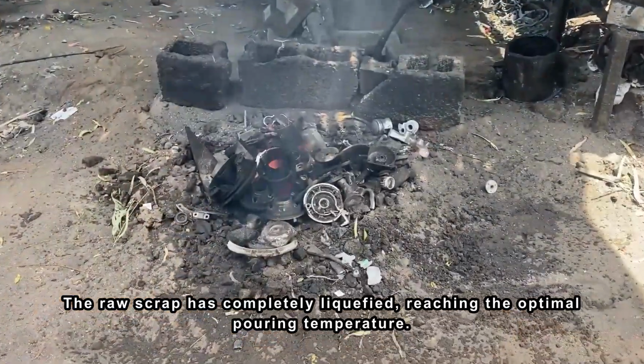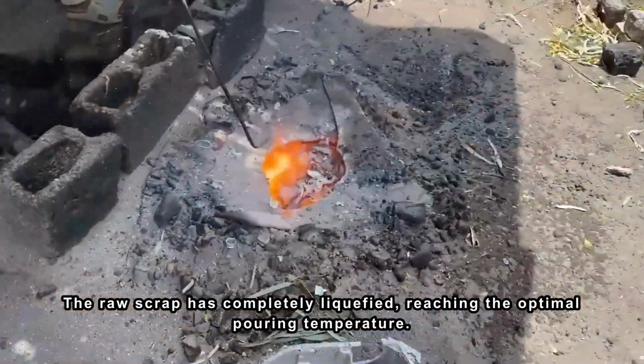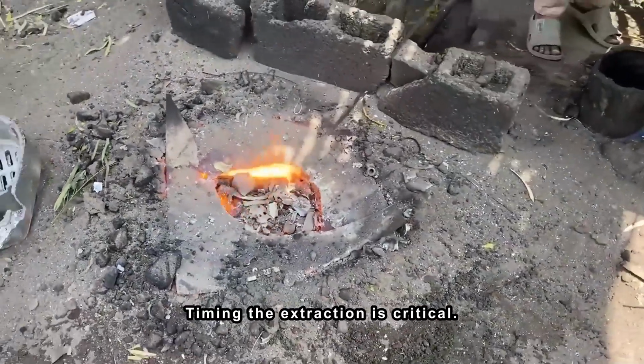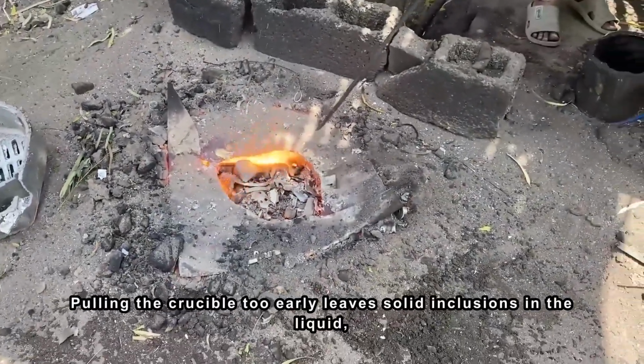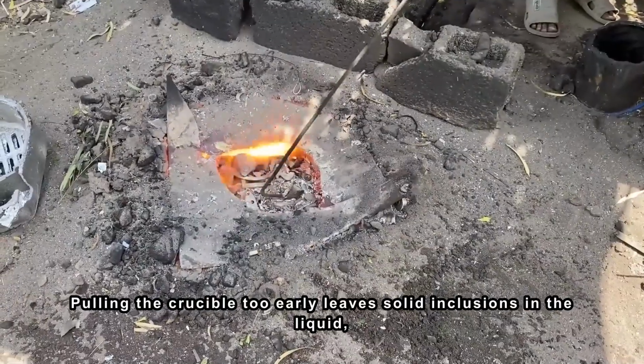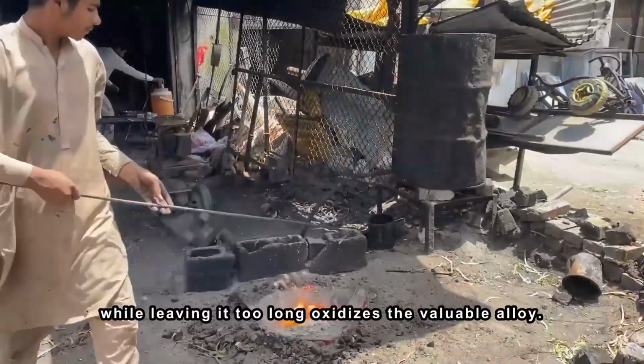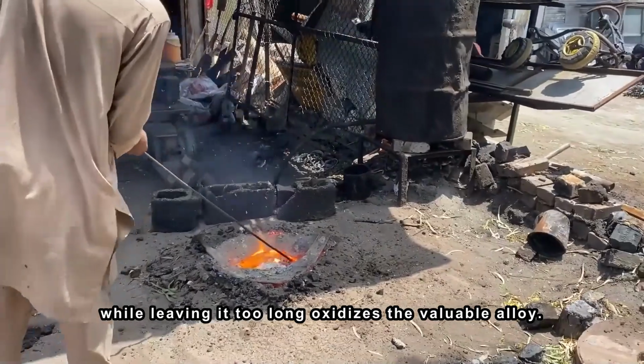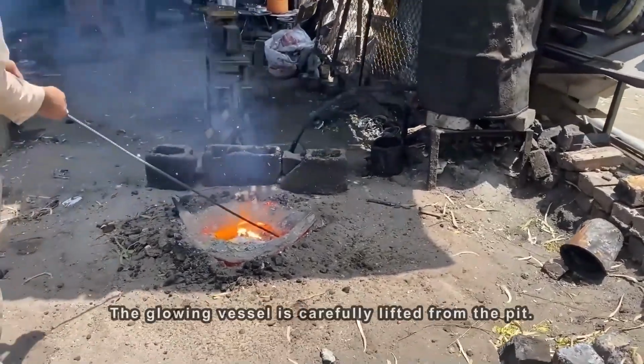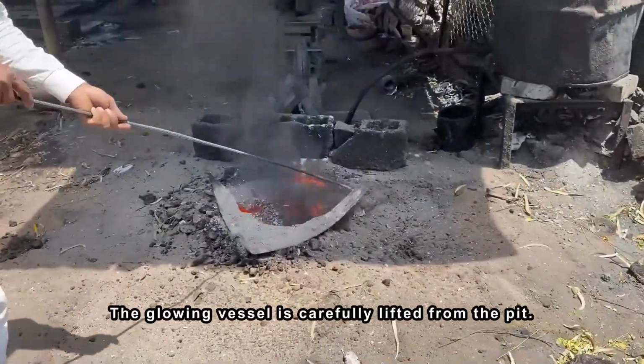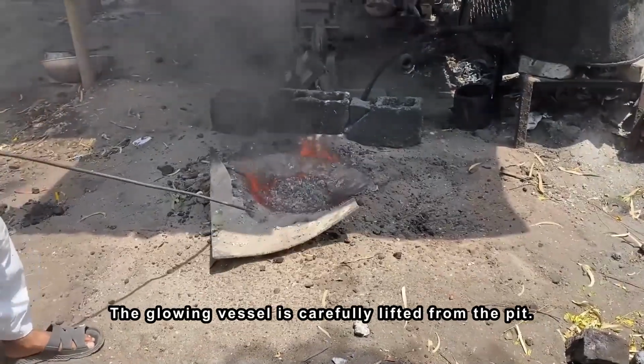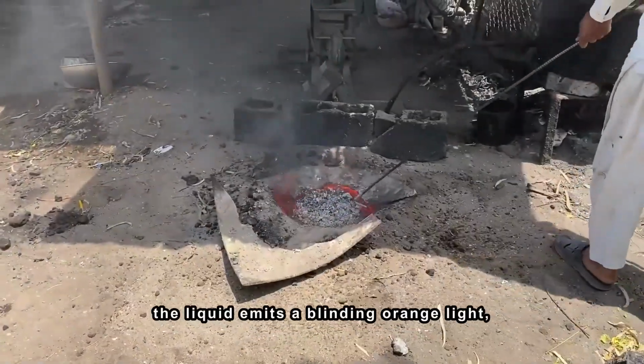Has completely liquefied, reaching the optimal pouring temperature. Timing the extraction is critical. Pulling the crucible too early leaves solid inclusions in the liquid, while leaving it too long oxidizes the valuable alloy. The glowing vessel is carefully lifted from the pit.